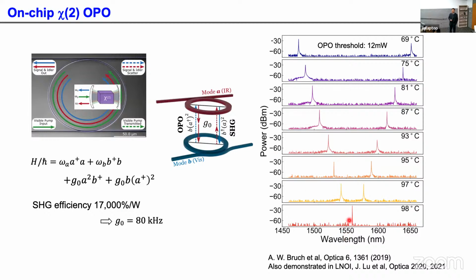You can also do down conversion and build an OPO. Kartik has done a lot of work on that too. The idea is that you split the photon using the same second harmonic generator. Instead of pumping at 1550, you pump at 775, and then you can build an OPO. The threshold is really low, a couple of milliwatts, and you can produce an OPO over a 120 nanometer wavelength spacing, so you can build a laser with this kind of OPO system. With lithium niobate, this threshold can be pushed much lower, to microwatts, because of the much higher optical nonlinearity. This optical nonlinearity is really determined by the fundamental-harmonic coupling. In our case, our 17,000% per watt corresponds to a single photon coupling rate of about 80 kilohertz.